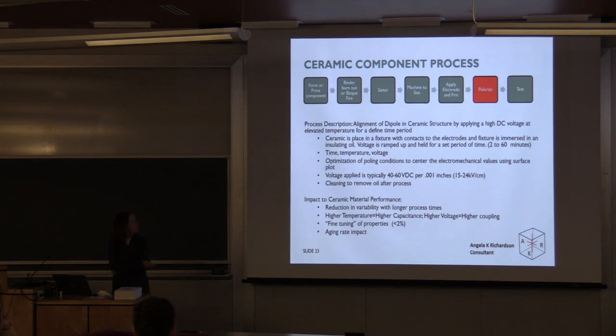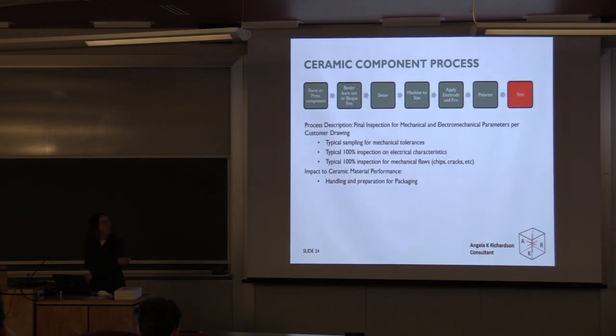The next step is polarization. We talked about that, aligning the dipoles. So the ceramic's placed in a bath of high dielectric oil. We apply a voltage to it, pretty high voltage, 40 to 60 volts DC per every thousandth of an inch. So it can be up in the 10s to 20 kilovolts. Then that ceramic is cleaned and ready for its final test.